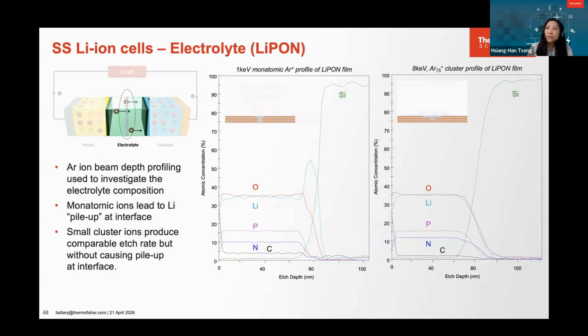From the very beginning, originally, people developed depth profiling using monatomic argon ion sources to remove the material. But for some time, it has been shown that it has some small problems. Sometimes it can introduce chemical changes to the remaining material, depending on the kind of material you're working with. The end result is a profile that doesn't reflect the true material, so it's distorted.